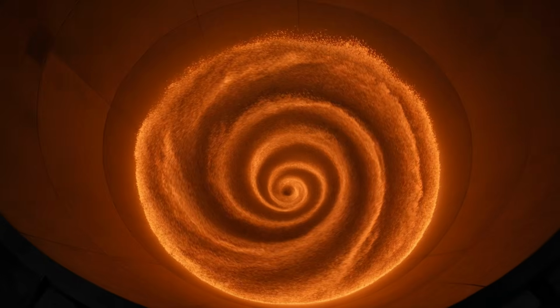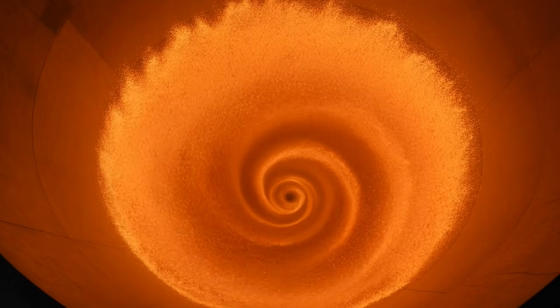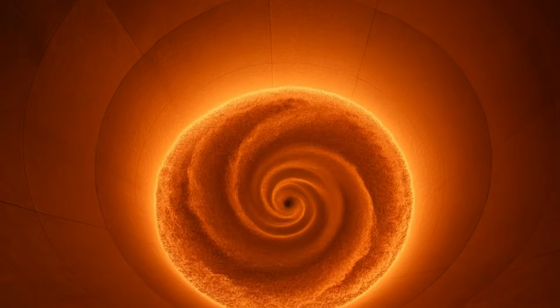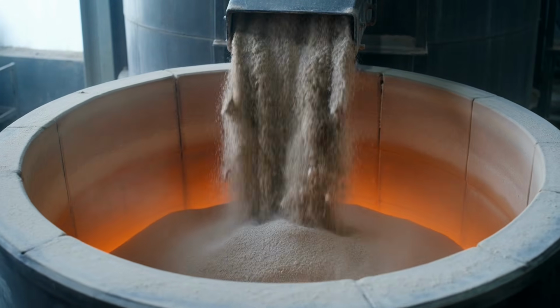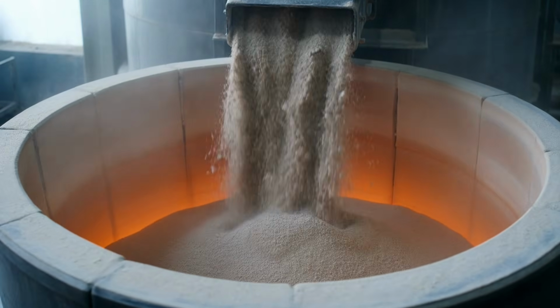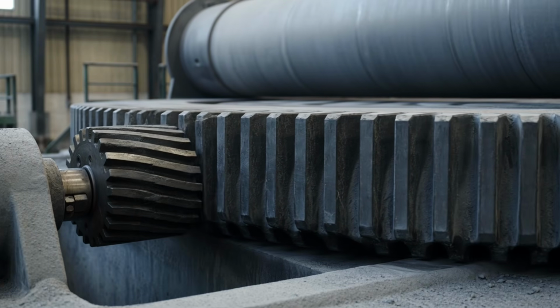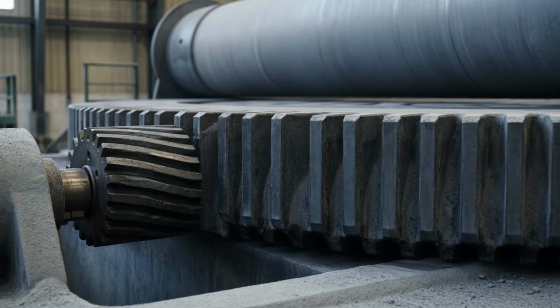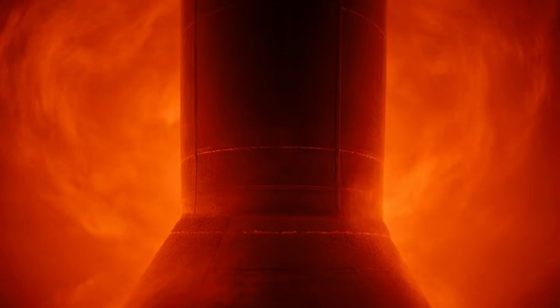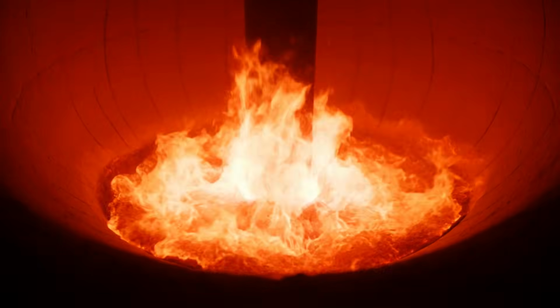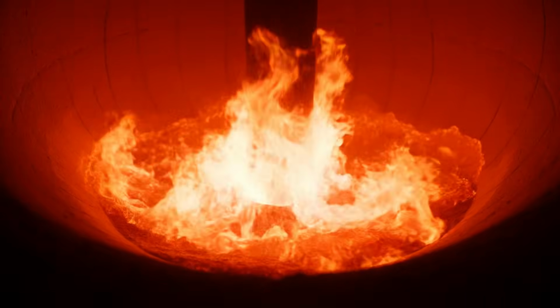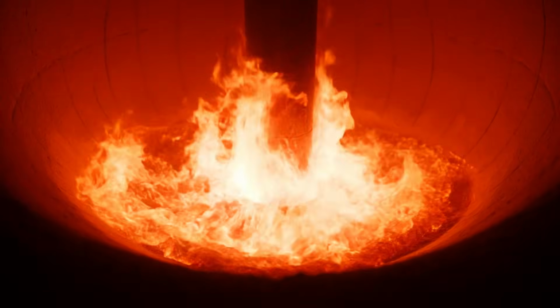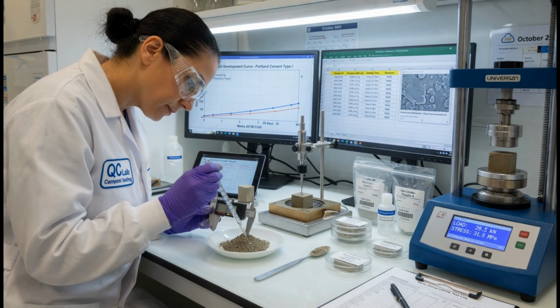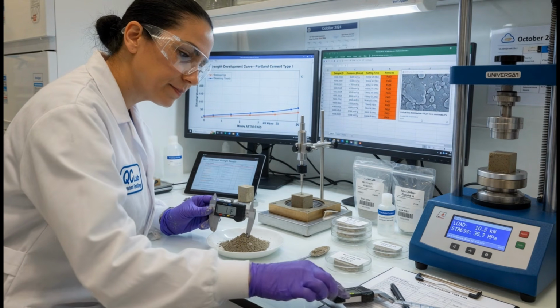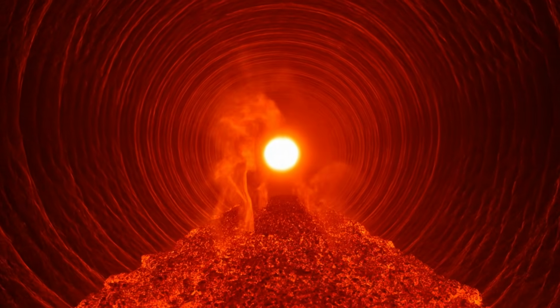Before the kiln, raw meal passes through this preheater tower, using exhaust heat to save energy. Inside each cyclone stage, hot gases spin the material, transferring heat progressively, stage by stage. Preheated and ready, the raw meal enters the kiln. From here, there is no going back. This ring gear, the largest in the plant, drives the entire kiln in rotation. Extraordinary power. At the far end, a central burner pipe blasts a continuous flame deep into the kiln barrel. The burning zone reaches 1450 degrees Celsius. Let that number settle for a second.